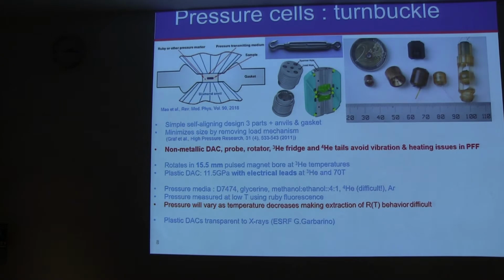We also have to be careful about hydrostatic levels. Not all of them are really hydrostatic. Usually we do not make resistance as a function of temperature measurements, because the pressure does not stay constant as you lower the temperature. There are many publications out there of resistivity versus temperature in pressure cells, and they never comment on the change of pressure as a function of temperature, but this is the reason why we don't do that kind of measurement. The last interesting point is that the plastic ones are transparent to X-rays. This allows full rotation of a sample in a beam, which can usually be difficult for X-rays.